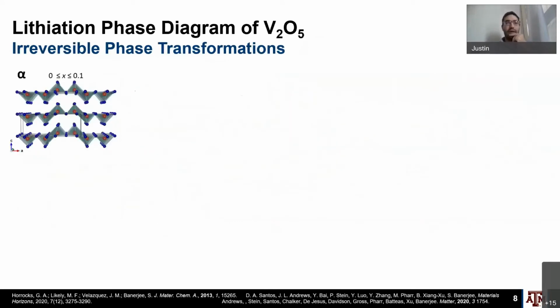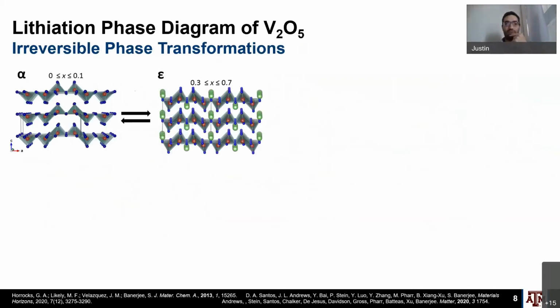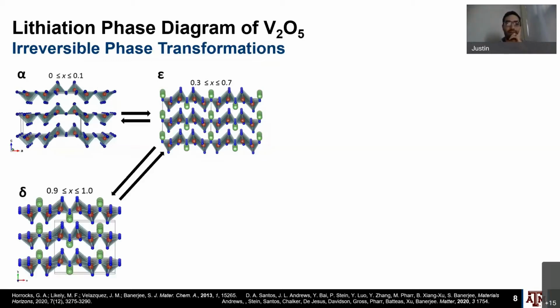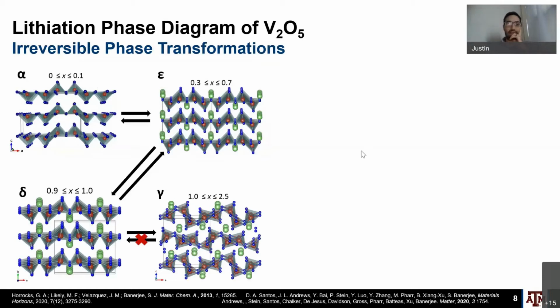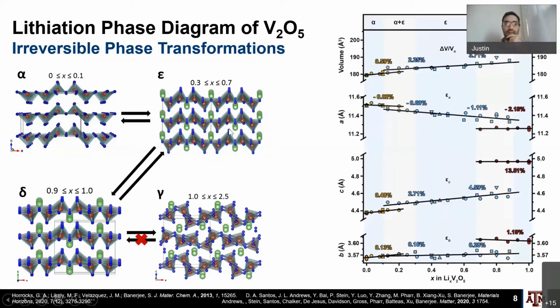But then on top of that, I also mentioned that the material undergoes a lot of irreversible structural transitions, and so as we lithiate alpha-V2O5, there's this immiscible region between 0.1 and 0.3 lithium. And then we nucleate this epsilon phase and then a delta phase. But then once we go above x equals 1 in LixV2O5, we nucleate this gamma phase, which is a total rearrangement of the structure, and we can't come back from that to access these phases.